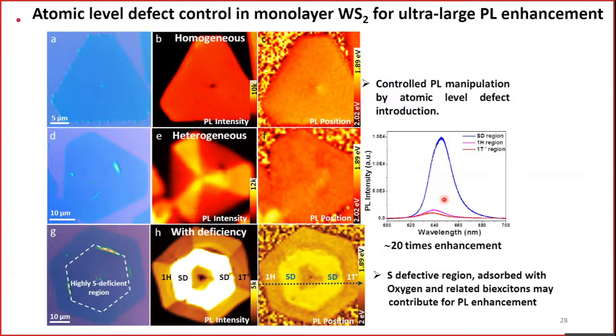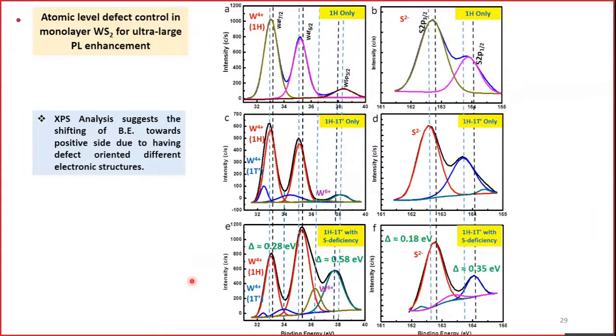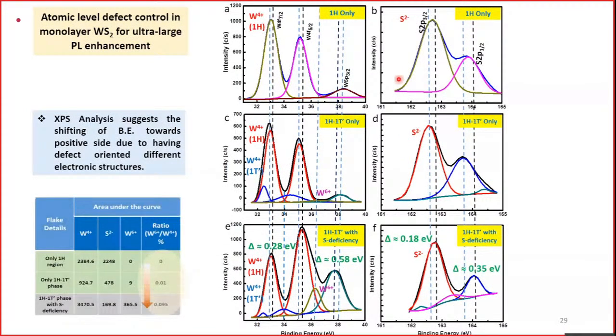affects the PL very closely. Compared to the difference between 1H and 1T prime that we observed earlier, it is a much higher enhancement when we have a severely sulfur deficient 2D material. Again, we confirm the sulfur defect, and we also try to quantify it. There is clear evidence of sulfur deficiency.